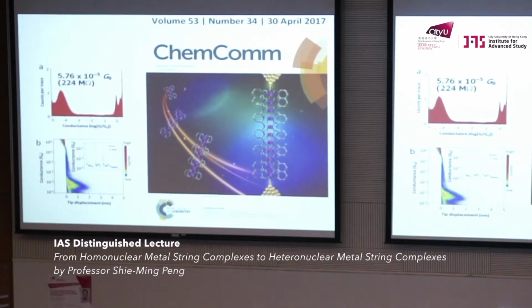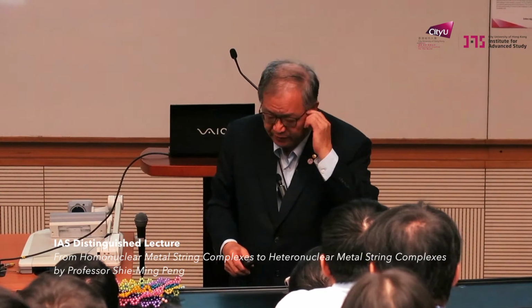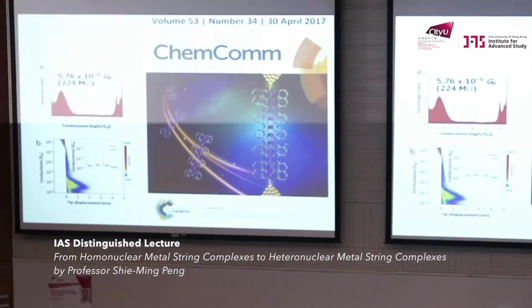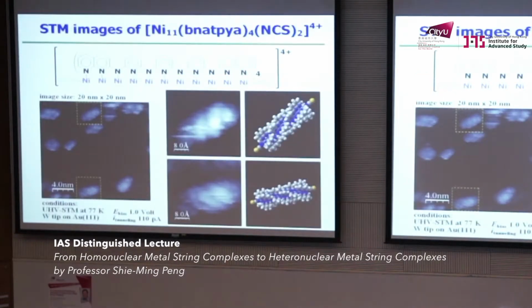So recently, we even made the pyridyl-naphthyridyl hybridized ligand. And we can use the STM, ultra high vacuum, low temperature STM to see the molecule. Because when you get longer and longer, the yield becomes lower and lower. It's very difficult to further purify or crystallize. So the simplest way is to see the molecule. This is an ultra high vacuum, low temperature STM. We really think we have to see this molecule, this other 11 nickel molecule.